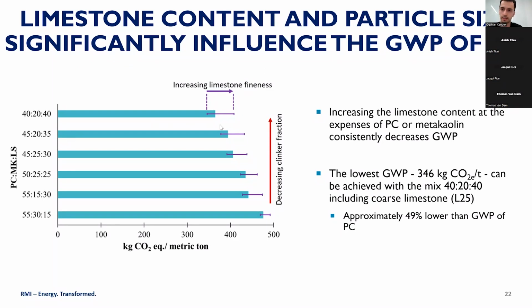Also, the finer the limestone is, the higher the global warming potential, because that requires a lot of processing, the grinding of limestone. So we want to keep the calcined clay content and the Portland cement content as low as possible. Also, we would like to use coarser limestone to achieve relatively lower global warming potential. But obviously, this will depend on the performance objectives.